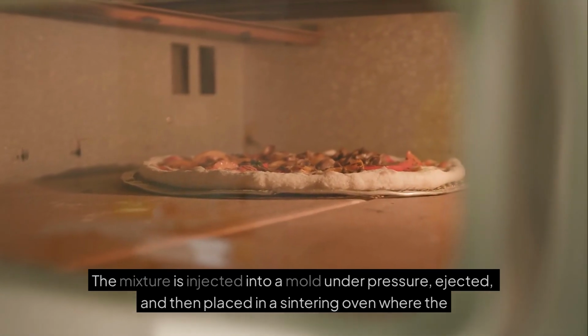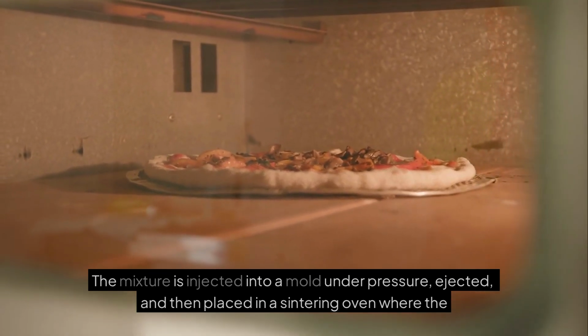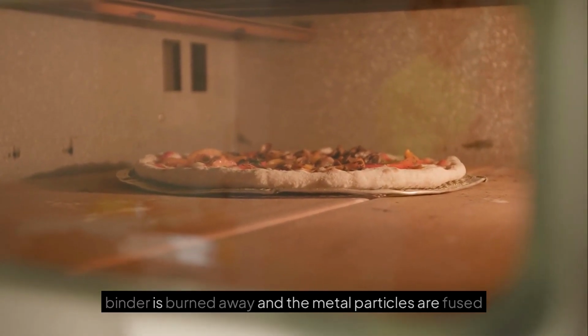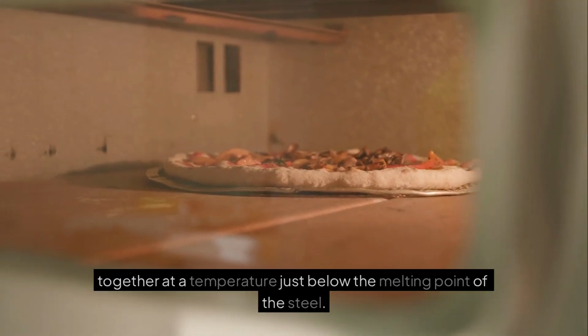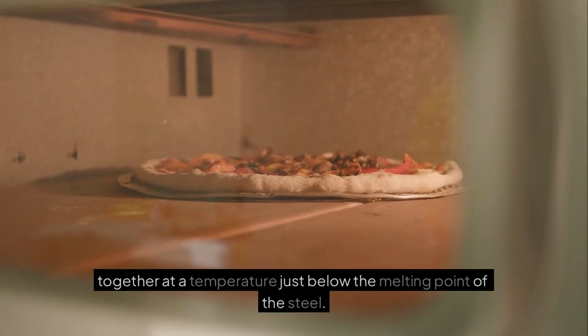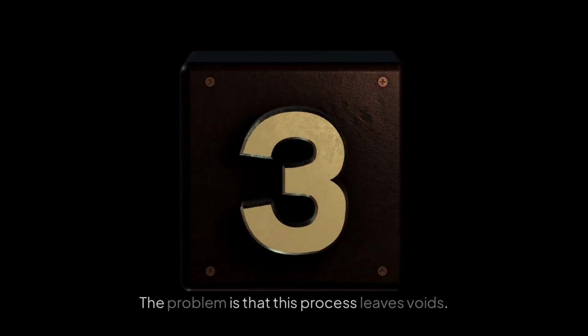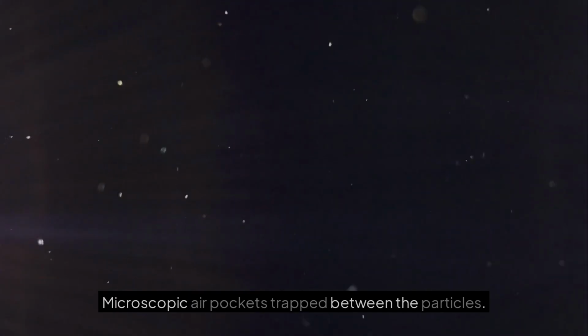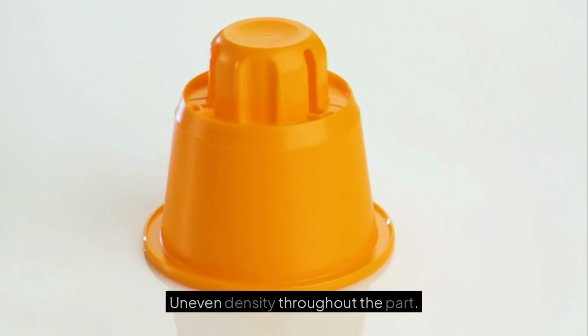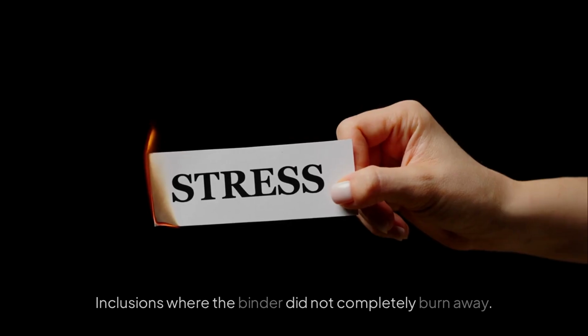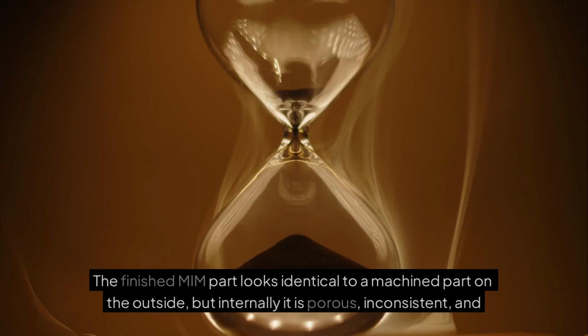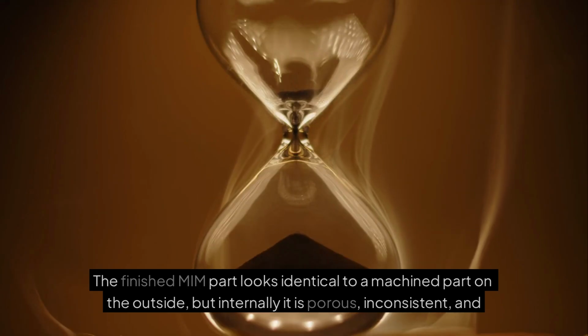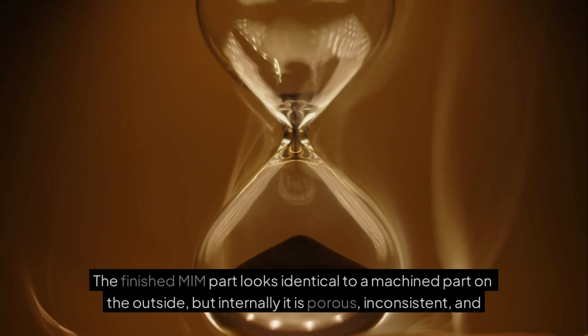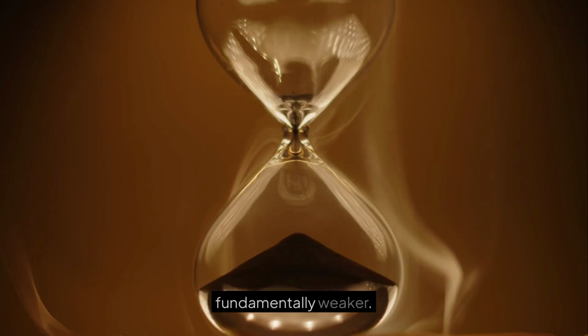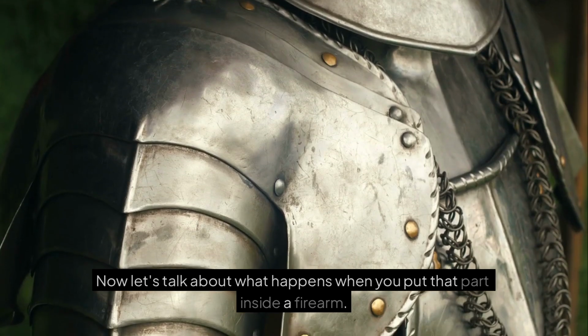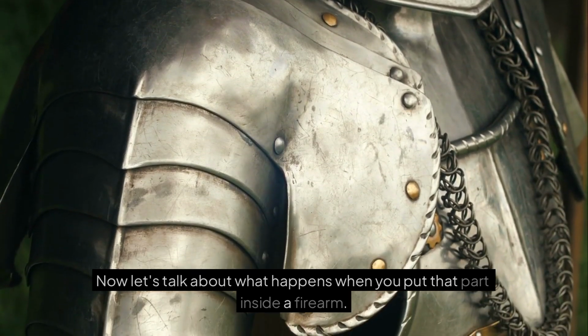The mixture is injected into a mold under pressure, ejected, and then placed in a sintering oven where the binder is burned away and the metal particles are fused together at a temperature just below the melting point of the steel. The problem is that this process leaves voids. Microscopic air pockets trapped between the particles, uneven density throughout the part, inclusions where the binder did not completely burn away. The finished MIM part looks identical to a machined part on the outside, but internally it is porous, inconsistent, and fundamentally weaker. Now, let's talk about what happens when you put that part inside a firearm.